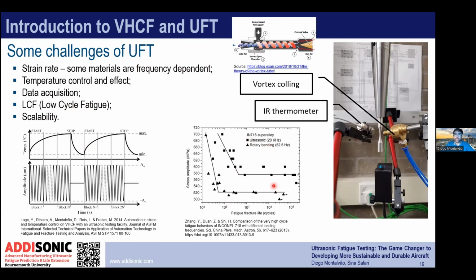Scalability as well, and how it compares, because of frequency-dependent materials, with normal testing. This is taken from a paper where they could see that there were some differences between the SN curves obtained in ultrasonic fatigue testing and obtained in rotary bending. But there are ways of calibrating the two curves, and from the ultrasonic data, converting it into the equivalent lower speed version. So that's something that is interesting to know. And some materials are more frequency dependent than others.